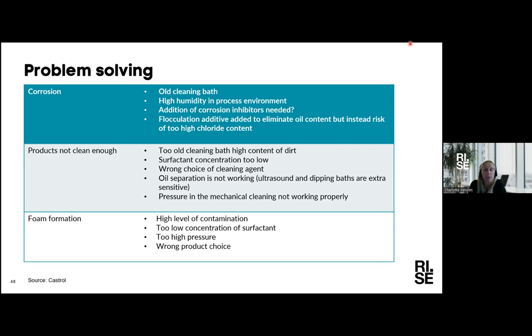And also there can be problems with foam, because if you get foam in your system, you had examples there on the washing equipment with spraying equipment with nozzles. So if you have too high pressure, for example, you can get foam, and it can be really difficult to get rid of that. Because with foam you don't have an efficient cleaning, so you want to eliminate the foam. That can be because of too old a cleaning bath, or too much contamination in the cleaning bath, or the surfactant level or concentration is wrong, and as I mentioned, the high pressure or even the wrong product choice. Maybe that's obvious, but